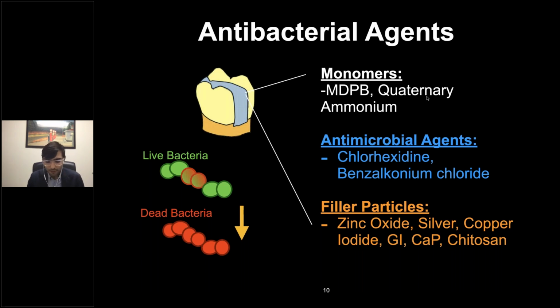The monomers, the famous ones are the MDPB, the quaternary ammonium is a classic one. As drugs and antimicrobial agents, we see chlorhexidine, benzalkonium chloride, and filler particles that are antibacterial are zinc oxide, silver as a classic antibacterial technology, copper, glass ionomers, calcium phosphates, and chitosan. So this is a big menu of antibacterial materials, and people have used these for a long time in different ways, as monomers, as fillers, and as drug coatings.